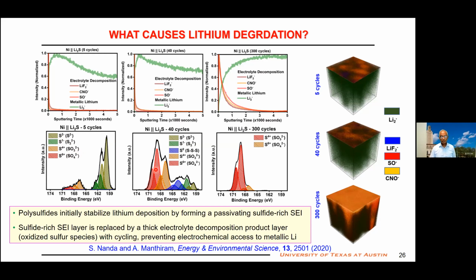By the time you go to 300 cycles, all the sulfide species is transformed or oxidized to these oxygen containing sulfate or sulfite species. That is insulating and that kills lithium metal cyclability. This is similar analysis with time-of-flight secondary ion mass spectrometry. All these oxygen containing sulfur species completely formed, compared to initially just on the surface, but it goes deeper, thicker, everywhere. So that is the problem. So what do we do?